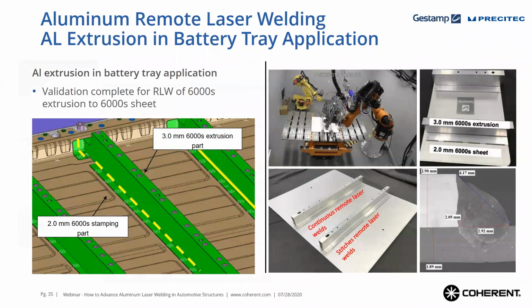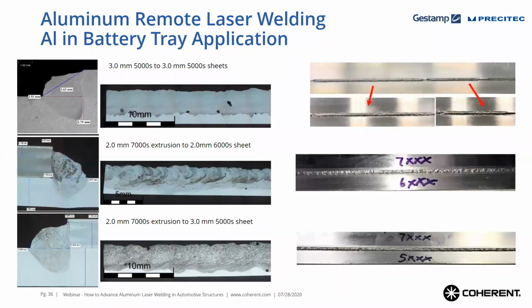Gestamp took it even further, where they looked at all kinds of different material combinations, whether it is 5,000 series aluminum to 5,000 series, this is your top image, to the center image, which shows a 7,000 series aluminum welded to a 6,000 series in fillet configuration, and then the bottom, 7,000 series welded to 5,000 series. You can definitely see that the center and the bottom welds are a little bit rougher than the top, which you would expect for 7,000 series. But it is an interesting result that they're able to successfully weld 7,000 series to other series, even in 2 mm thickness, which is also pretty thick.